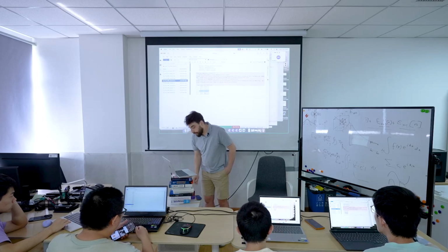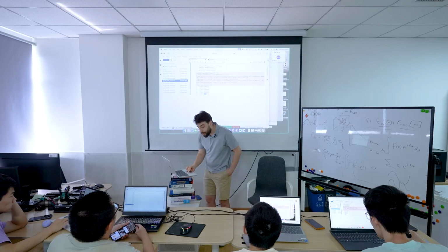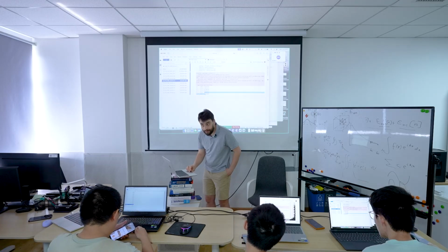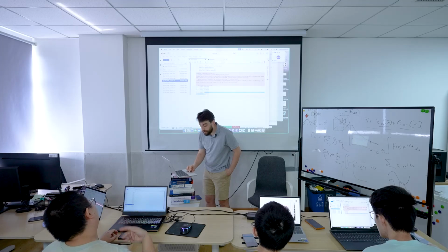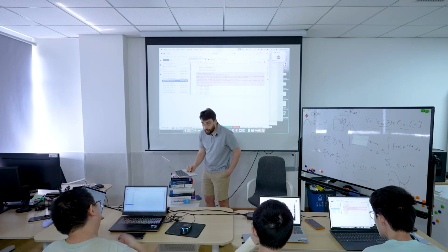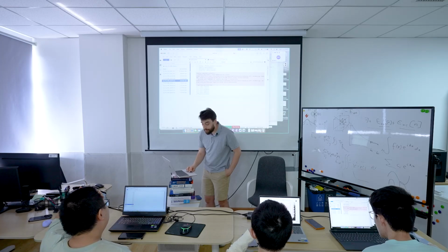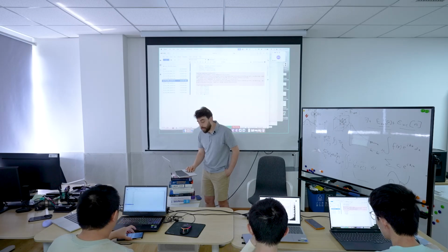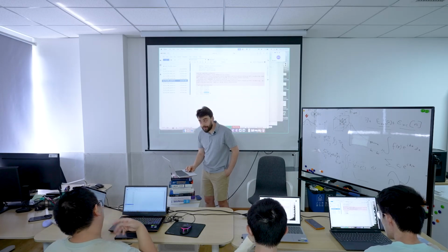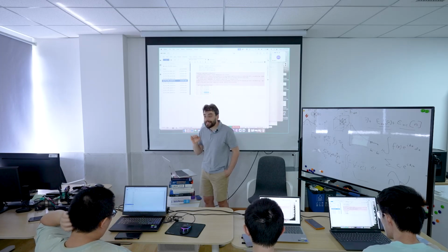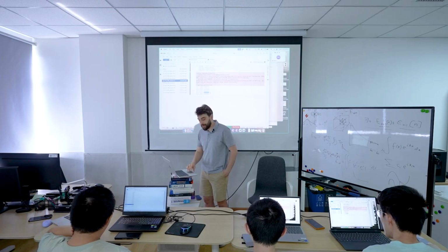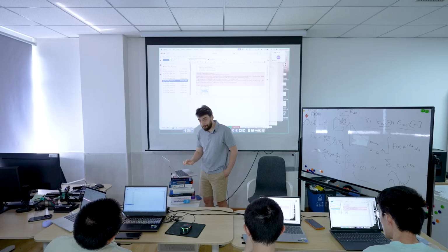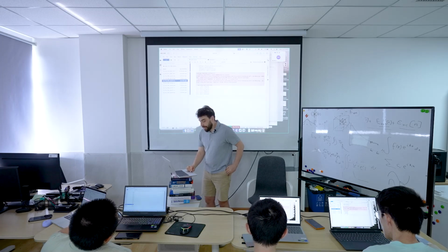Okay. Right, so there's our 6 by 6 by 6, and you can see that 6 by 6 by 6 is the one we would really, sorry, 5 by 5 by 5 is the one we should be picking, right? You can see the difference between 6 by 6 by 6 and 5 by 5 by 5 is approximately 10 to the minus 2. Okay, so basically 5 by 5 by 5 and 6 by 6 by 6 energy is the same to within 10 to the minus 2. So that is good enough. Okay, but for this class, 5 by 5 by 5 is too slow. So we're picking 4 by 4 by 4. Okay, all right.